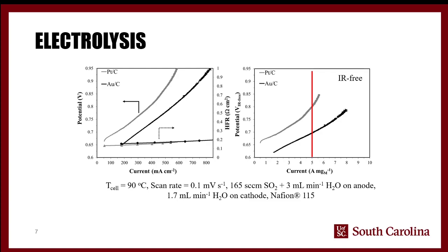So in terms of the conditions here, we held the temperature of the electrolyzer constant at 90 degrees. The scan rate on the current potential curves here was 0.1 millivolts per second, so very slow, which effectively allows us to find a steady state value for each potential. And that is important because if you scan it too quickly, it takes an electrolyzer, in this case, a 10 square centimeter electrolyzer, some time to reach an equilibrium every time you change the potential that's applied or you change the current that's applied.